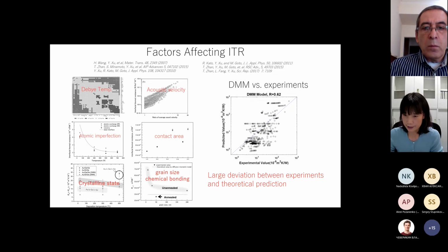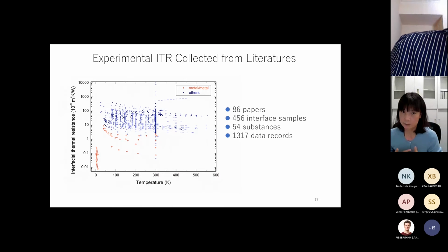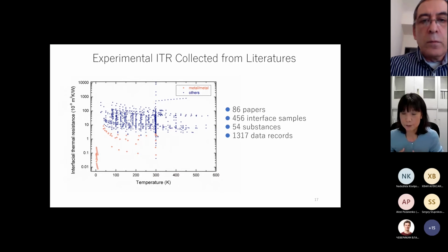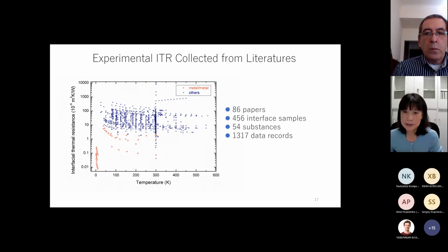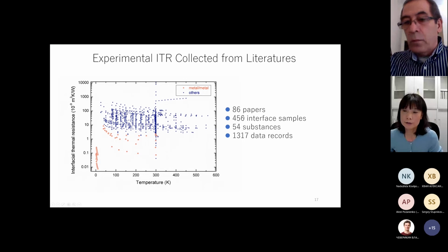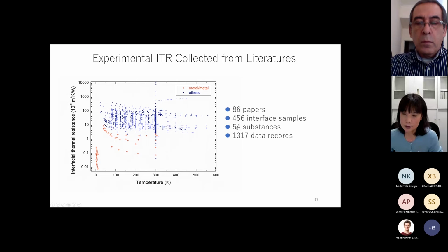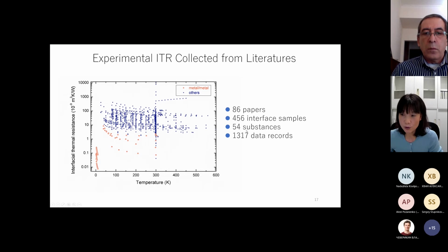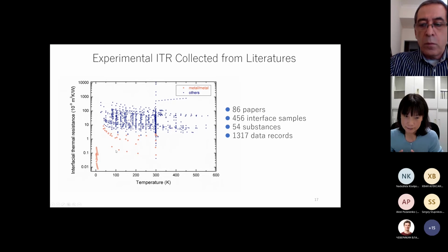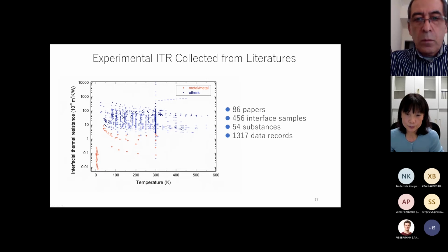Then we try to use a machine learning model to predict the ITR. So we started by collecting experimental data from papers, and actually we collected data from 86 existing papers, which include 456 samples, and they are composed of 54 substances. And finally, in total we have more than 1,300 data points.